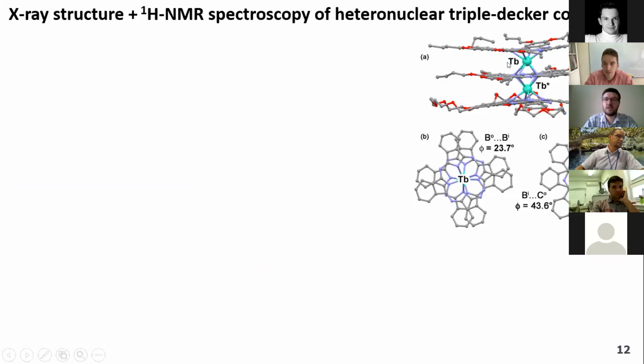For example, we succeeded in getting single crystals of this triple decker, and we saw that the terbium ion, which is located between the unsubstituted and butoxy substituted ligand, has a square antiprismatic coordination polyhedron, nearly perfect. And the terbium ion, which is located between butoxy substituted ligands, is in a distorted state. So it's something between square prismatic and square antiprismatic.